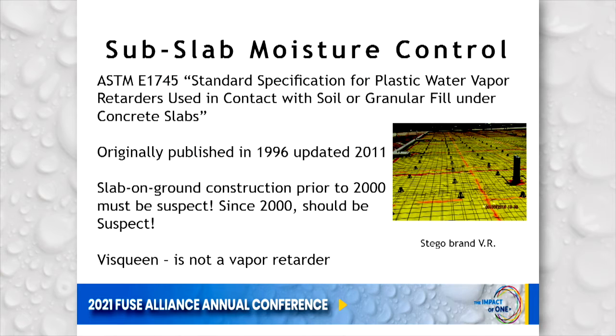So when we talk about looking particularly at older constructions, it's fair to say that any slab on ground construction prior to 2000 must be considered suspect. There's likely not an effective vapor retarder under it. Anything since 2000 still should be considered suspect. And the one thing I'll say emphatically is visqueen, if you see that in a specification, is not a vapor retarder. Typically it's clear plastic, and as this picture on the right shows, which is a Stego product, our high quality vapor retarders typically have color, Stego being yellow.